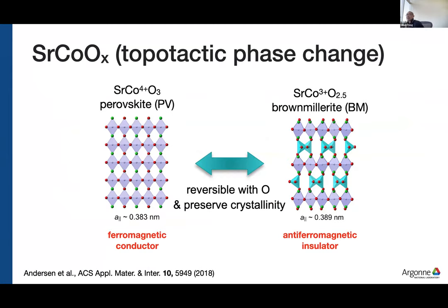I think my favorite system right now is strontium cobaltite. It undergoes a topotactic phase change from the perovskite, or sometimes I say the 113 phase. The perovskite, of course, is made of all oxygen octahedra. When you remove some of the oxygen, you form the Brownmillerite phase, which is the 112.5 phase. It's nice because you can switch between these two phases topotactically, so there's almost no effect on the crystal quality. At the same time, you're changing it from a ferromagnetic conductor to an antiferromagnetic insulator.